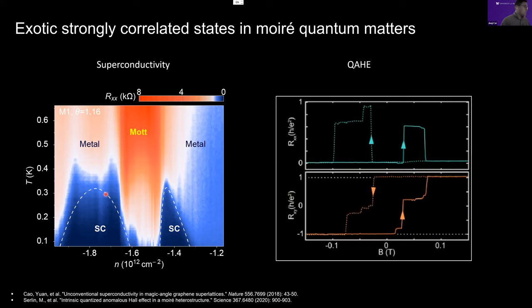Another piece of evidence is about the topology of the system. Actually, at the electron doping side, people found emergent magnetism inside the system, and also the corresponding quantum anomalous Hall effect in twisted bilayer graphene additionally aligned to a hexagonal boron nitride substrate. Okay, so what you can see here is there are two effects. One is you twist two non-magnetic materials, and surprisingly at low temperature, it spontaneously breaks time reversal symmetry and develops ferromagnetism, as noted by those hysteresis loops. Another effect is that the band topology gives rise to this Hall effect, or quantum anomalous Hall effect. So these are two very nice observations of the system.